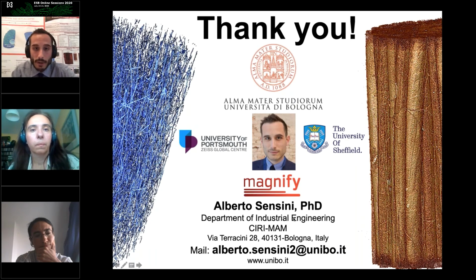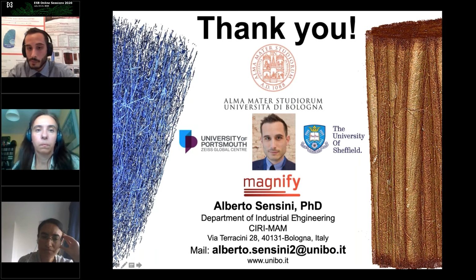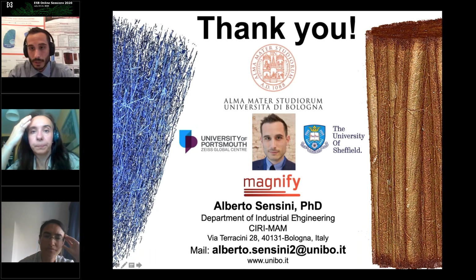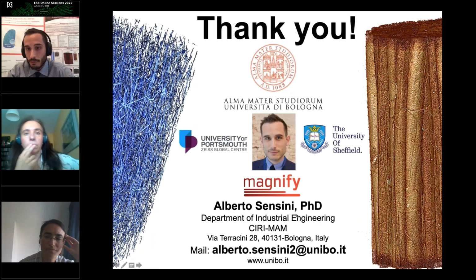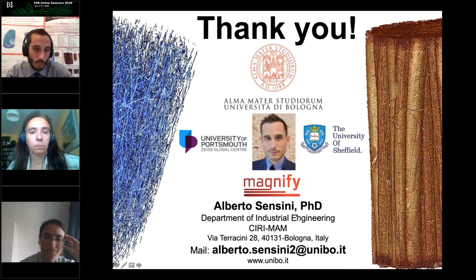Basically, we tested the degradation and the permanence in PBS for our scaffold at the moment, following also the degradation process, up to 14 days. What we saw basically was that the main problem was the loss of collagen, because the PLA more or less maintained - it doesn't degrade too much during these periods of permanence in physiological environment, cell culture medium. Again, the main problem was the collagen in the degradation, which we fixed with the cross-linking procedure that you saw.